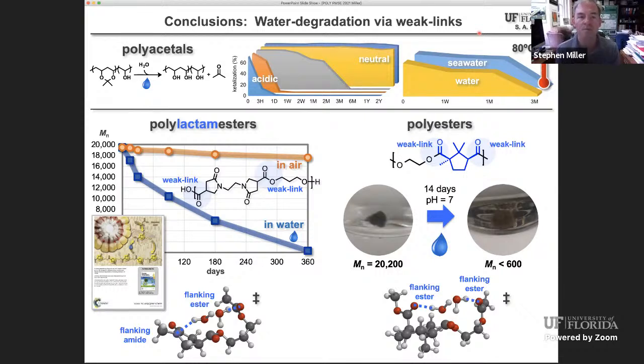And once you do that, you have some hopes of recrystallization, and then you're not really worried about exactly what its source was, because you can get it relatively pure and then use it as a monomer for making a nice linear polymer. So that's kind of our overall scheme, is to make nice linear polymers, which means you do generally rely on fairly discrete molecular things to start with. There are different realms of where people make things. Some people attach things to existing biopolymers and they can make really cool materials that way. We like the idea of making melt processable materials, which generally means non-cross-linked linear polymers, because we want to injection mold them and form them into the next water bottle. That's sort of our area. And as chemists, we love to be able to dissolve our polymers and understand them, and understand really what they look like in solution.